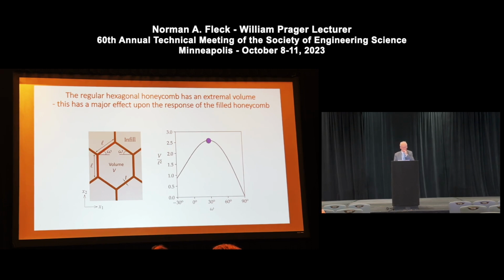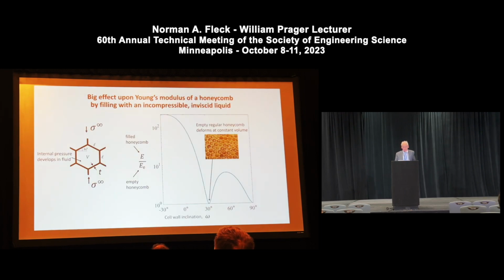So that is telling us something very important. It's saying that fundamentally, the lattice, I think it was pin jointed, can easily deform by a mechanism. But once it gets to its maximum inflated state, where omega is 30 degrees, if I continue to try and deform the structure, the volume can only decrease. So we have to switch mode to a stretching mode at 30 degrees if we were going to continue to try to expand the lattice. The consequence of that is huge.